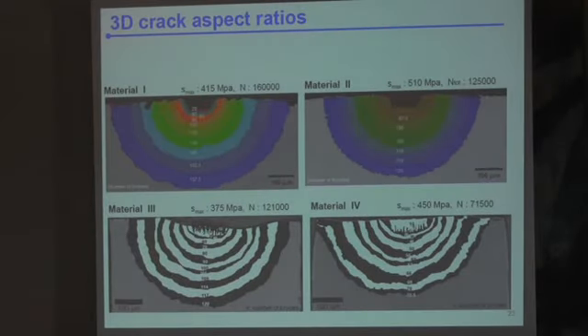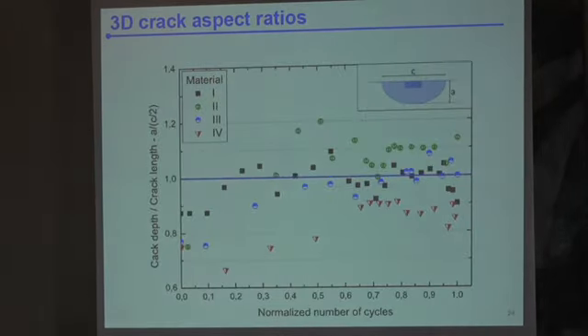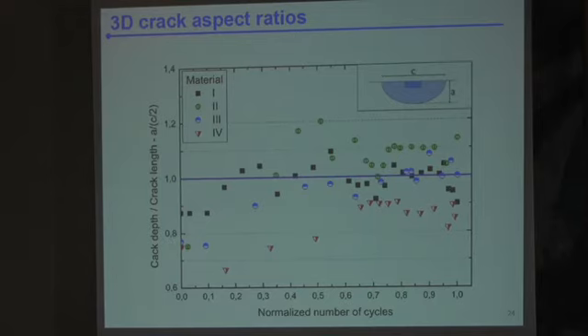Now, as I said, we did see a difference in the crack shape in that case and not in the other ones. They are all summarized here. I think maybe when you compare them on the single slide, it's more obvious than what I said before, that the angle is slightly different in that case. So in terms of crack ratio, this has an influence.